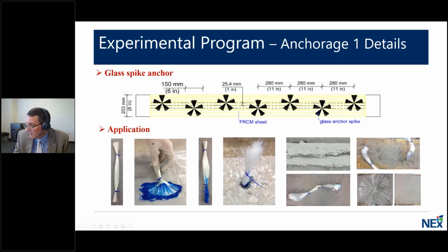It's wrapped up because we feed this through the PBO fabric, and then, of course, fan it out, and then put it on top of the final placement of the cementitious mortar system. So this is the glass spike anchor system, and on top is shown where the anchors were applied.